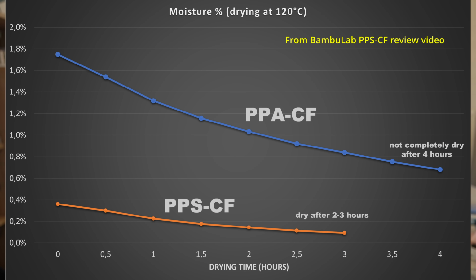About moisture sensitivity, PPS is less sensitive to moisture compared to the PPA, and actually I tested this earlier from different brands, and PPA is less sensitive compared to the PA12 or even PA6 from the nylons, but adding fibers to it will always increase this sensitivity. In this case, glass fibers. Now, glass is not sensitive to moisture, right? But a combination of two will always increase a little bit this sensitivity.